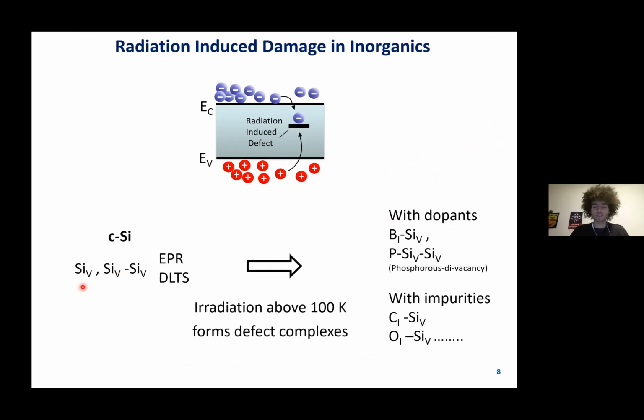But then, and this is quite crucial, if you are at temperatures above 100 Kelvin, these silicon vacancies start to complex with dopants in the silicon or with impurities in the silicon, and you start to form these phosphorus divacancy complexes or carbon-oxygen vacancy complexes, and these are particularly harmful and degrade any solar cell.